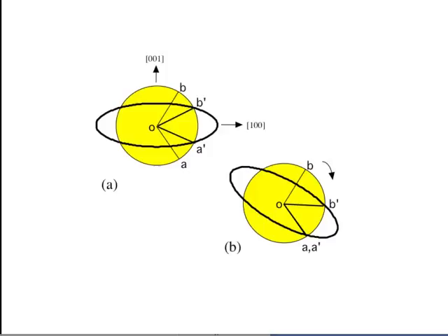There are two vectors which are unchanged in length, right? Why do you say no? Yeah, so they are rotated. Invariant means unrotated and undistorted. Okay? Now, I can recover. So the Bain strain basically does not leave any line unchanged. Therefore, we cannot satisfy the minimum condition for martensitic transformation that we have an invariant line.